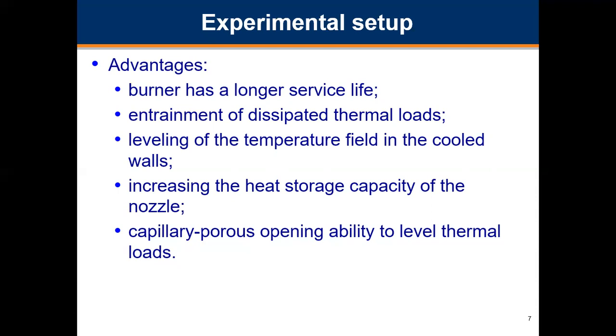Thus, the temperature field in the heat-stressed elements of the burner is leveled and the appearance of sharply varying destructive loads is excluded. The listed advantages are realized both at nominal load and in alternating and emergency operation modes. No blockage of the cooling cavity by steam bubbles. Coolant consumption is drastically reduced by a factor of 4, which saves water.